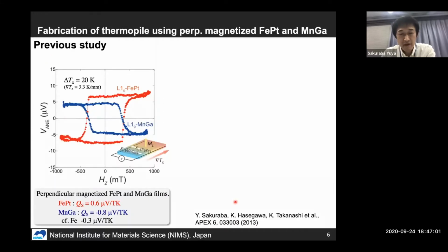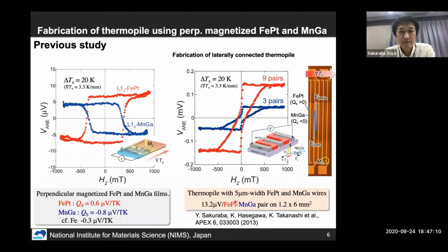But anyway, in my previous studies that I performed with Professor Takanashi almost 10 years ago, I made a prototype of a thermopile structure using the anomalous Nernst effect. In this study, because iron platinum and manganese gallium have opposite signs of the anomalous Nernst coefficient, I made a laterally connected thermopile structure consisting of iron platinum and manganese gallium wires. In this study, we successfully demonstrated the enhancement of the output anomalous Nernst voltage depending on the total number of pairs of iron platinum and manganese gallium wires.